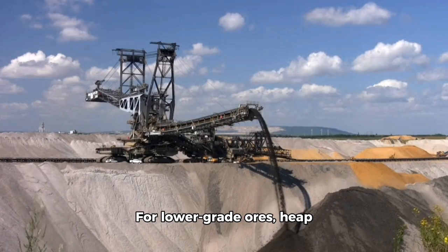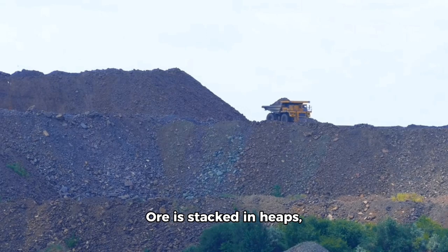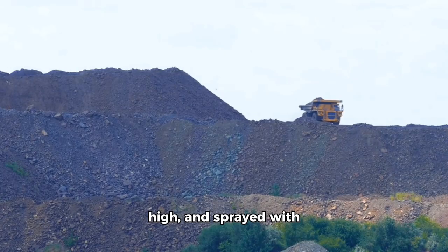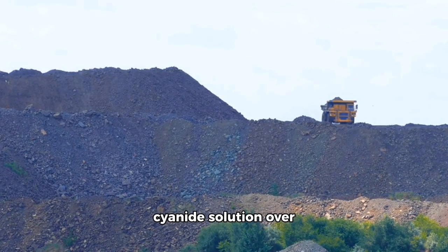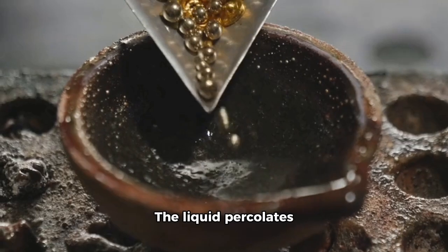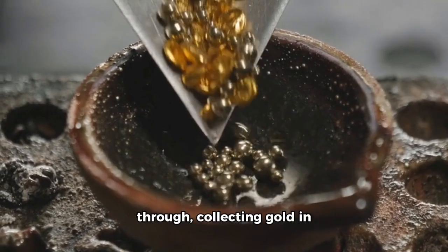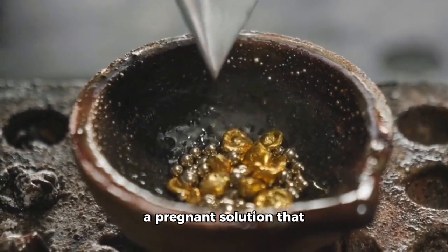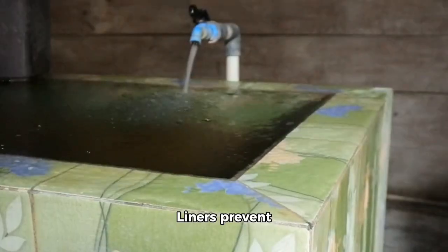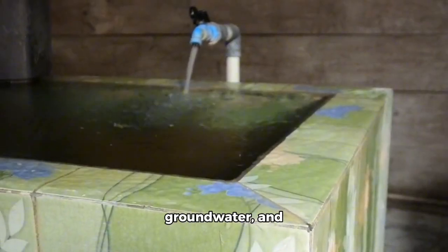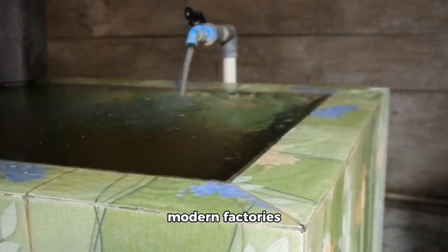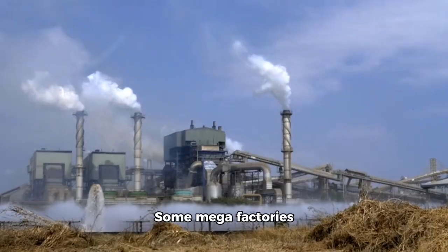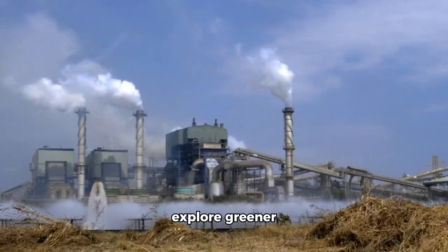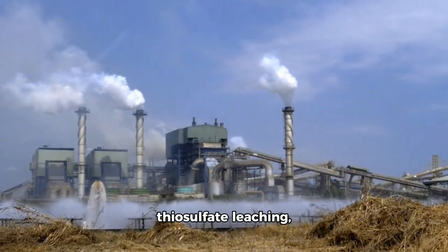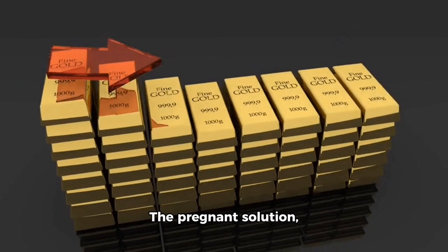For lower-grade ores, heap leaching offers a cost-effective alternative. Ore is stacked in heaps, sometimes 100 meters high, and sprayed with cyanide solution over weeks or months. The liquid percolates through, collecting gold in a pregnant solution that drains into collection ponds. Liners prevent contamination of groundwater, and modern factories recycle 70% of the water used. Some megafactories explore greener alternatives like thiosulfate leaching, which avoids cyanide but is less efficient.